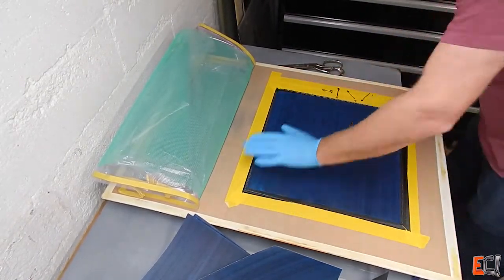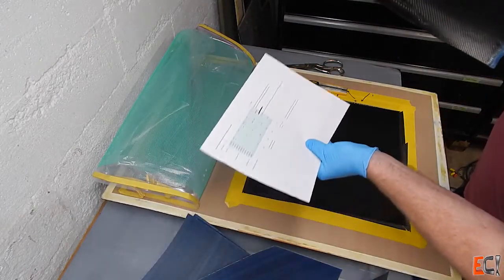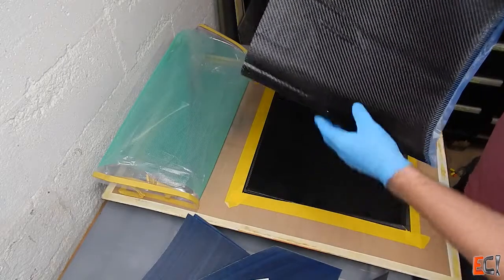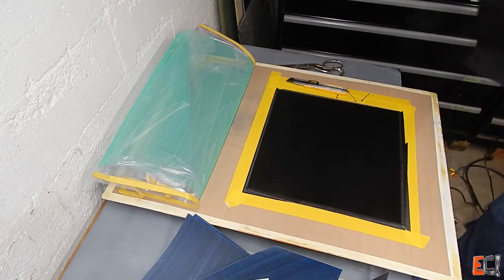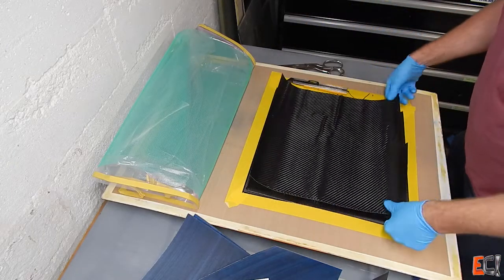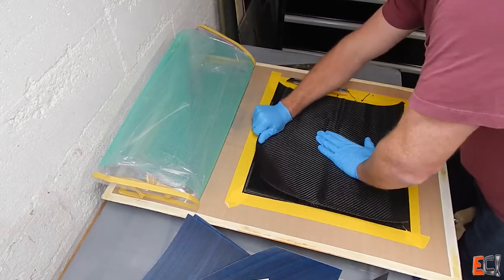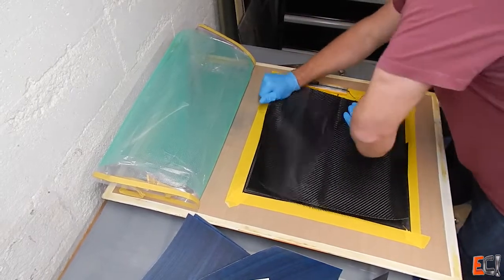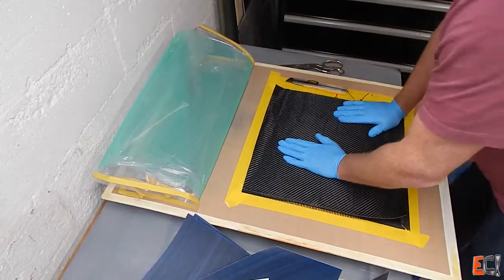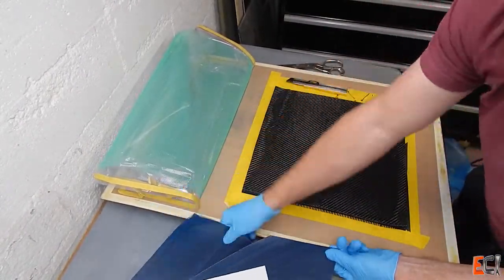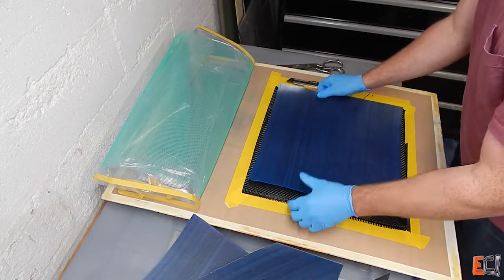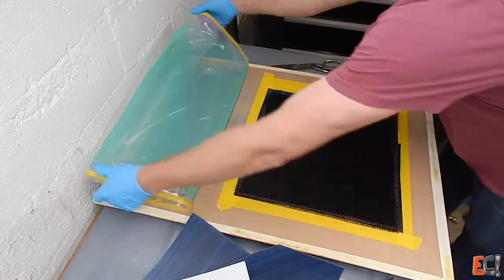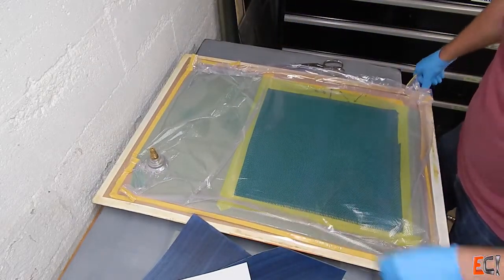And we'll go down. And now we've reached the center ply at the neutral axis and here I am making a mistake putting down a 0 or 90 when I should be putting down a plus or minus 45 layer of this 200 gram twill. So my laminate will not be exactly quasi-ISO as much as it could have been. There will still all be the right amount of uni pointing in each direction but I've got it off now by more than I had planned.